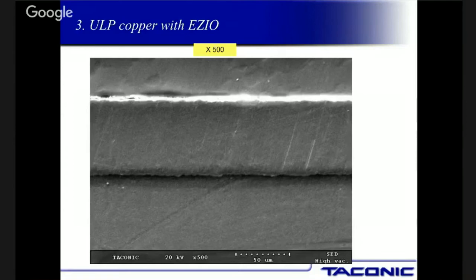Less property dispersion, is that right? The phase velocity will stay. Yes, in fact, the phase velocity and everything stays very constant. The issue is when they're doing a design, and you guys do the same thing. When you have a 120 mil wide trace, you don't want any nicks, dings, scratches, anything on that, because you want to maintain a controlled impedance across the board. And it's the same thing with those 2 mil lines and spaces. They don't want 2 mils plus or minus a half a mil. They want 2 mils with no dings, scratches, nicks. They want very straight sidewalls all the way down the whole trace over 24 inches. And with these new coppers, you can get that, also with a good board shop.